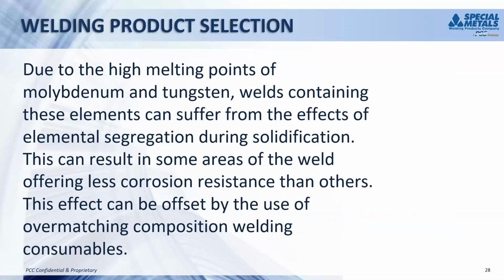Obviously, if we're building these systems out of corrosion resistant alloys, we want the welds to be as corrosion resistant as the base metal. The nickel chrome molybdenum welding products can suffer from the effects of elemental segregation during solidification. Molybdenum and tungsten melt at very high temperatures. Thus, when a weld is solidifying, those elements are the first to solidify. So the part of the weld that solidifies first will be enriched in molybdenum and tungsten, whereas the material that solidifies last will be depleted of those elements. So you can see some variation on a micro scale across a weld due to these elemental segregation effects. The best way to offset that is to use an overmatching composition welding consumable.